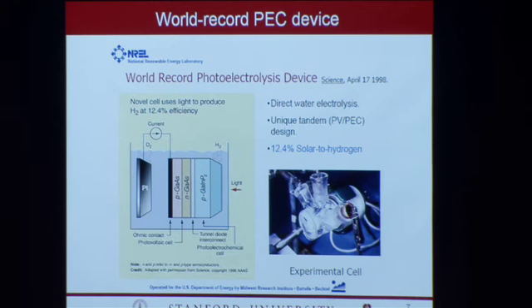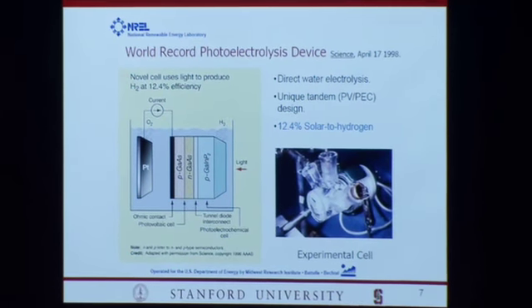Now, the problems with this material are twofold. Number one is it's extremely expensive. We're talking about on the order of about $50,000 per square meter for that type of material. So clearly, you're not going to be layering this on rooftops or whatnot. Number two problem is it's not very stable. It turns out that there's a cathodic corrosion process that happens on that surface, so it degrades after about 20 hours.